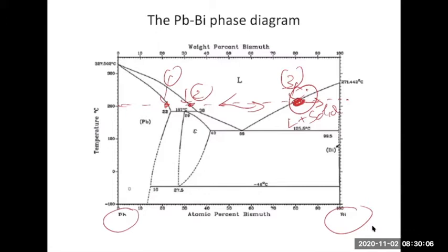So that point at 200 degrees, I think I drew this line slightly off, because I know we're closer, because this point here is 200. My line wasn't very straight. So it's actually this point. So in reality, it's about 72, 73% at 200 Celsius, 473 Kelvin. So what's remarkable is how close we are, right, with an enormous level of approximations.